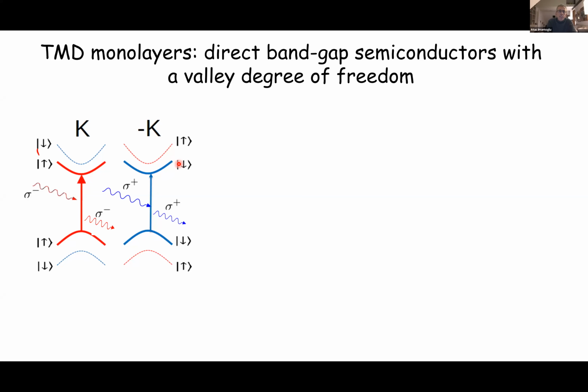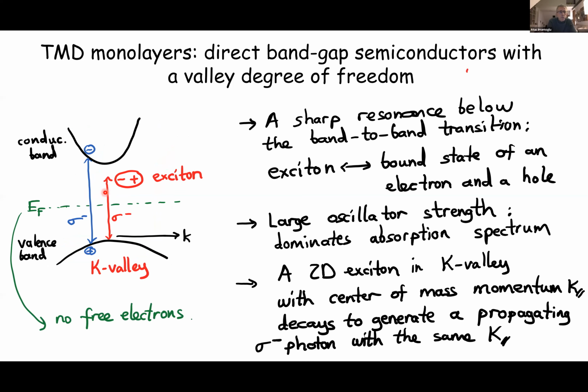Now, in most TMDs, though, since spin-orbit coupling is relatively strong, the spin is locked to the valley. And in that sense, we still deal with excitations with two degrees of freedom unless we increase the electron density and basically start occupying the higher energy state. So this splitting in the conduction band is about 30 milli-electron volts. In the valence band, it's about 200 milli-electron volts for molybdenum diselenide. So let's focus on only one valley, say the K valley.